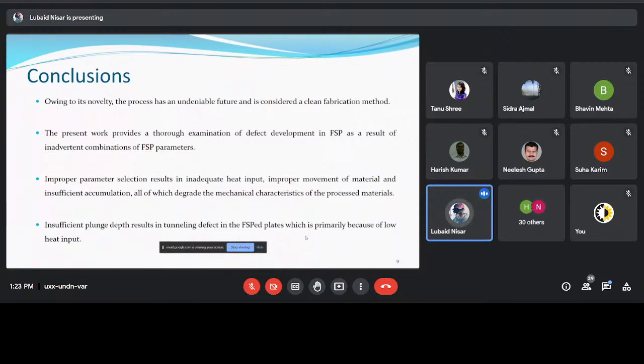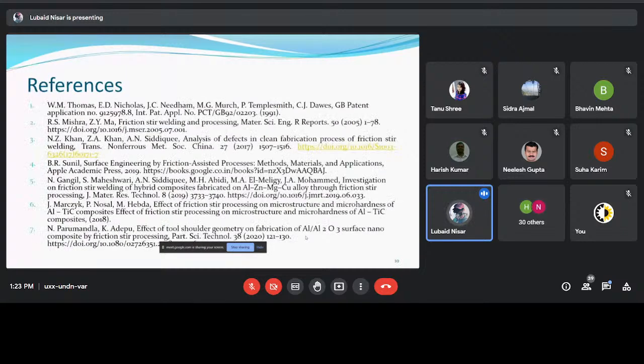Insufficient plunge depth results in tunneling defect in the friction stir processed plates, which is primarily because of low heat input. These are some of the references.